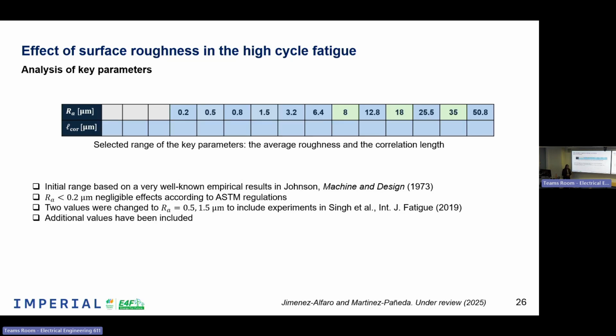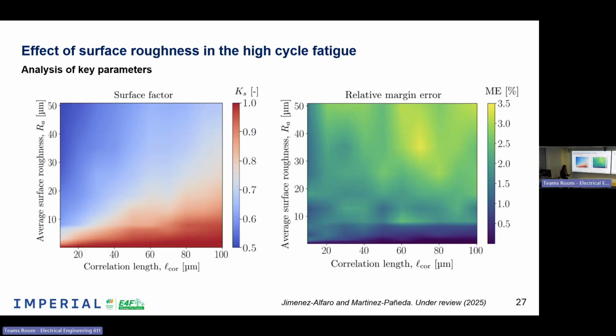And we have also included additional values to really capture the evolution of the surface factor with respect to these 2 parameters. We can do it. This is an advantage of our computational tool, that we don't spend a lot of money. We just use a calculation cluster, so we can include as many parameters and as many values as we want. And finally, we have decided the range for the correlation length based on a proposal in the literature. So now we have built this kind of operational map. You can see here that we represent the surface factor as a function of the average surface roughness with respect to the correlation length. For very low values of the correlation length and very high values of the surface roughness, we get a surface factor that is around 0.5.